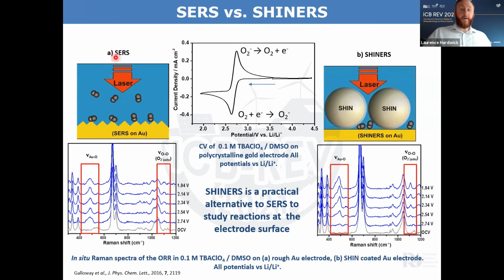And so we can compare our SERS result and our SHINERS result. With the SERS, we can reduce the potential, and we can see a band related to the oxygen-oxygen stretch of superoxide, and at the same time we have the adsorbed superoxide species from this gold-oxygen stretch as well, which is appearing. Then when we repeat this with our SHINERS particles, we see these same bands appearing, demonstrating, in our first work on this, that SHINERS is a practical alternative to surface enhanced Raman in these systems which are pertinent to lithium oxygen systems.